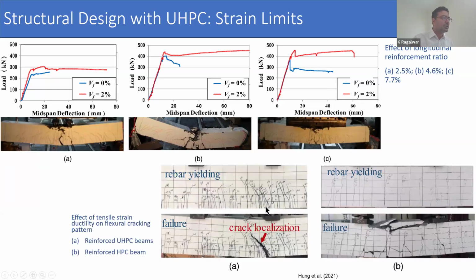So this is also a good plot which shows how the behavior is different in UHPC and in a reinforced high strength concrete beam. Here we see lesser number of cracks and concrete crushing. Here we see that crack localization leads to fracture of reinforcement in the fiber. So the failure modes are very different based on presence of fiber. And that's why, when and where does the crack localization occur under flexure loading is difficult to answer. As a design guideline, they try to cap it, but also take into account that we are considering the block under tension at least up to crack localization, because if we ignore that, then we are not utilizing the material to its fullest.